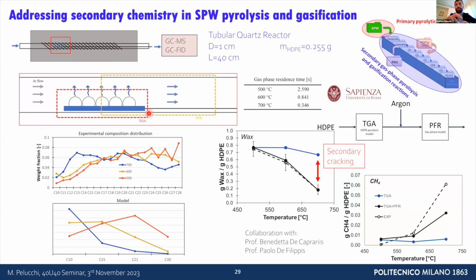So how do we model the system? Not only with a TGA, but we need to feed what comes out from a TGA to a flow reactor model, like in a simplified chemical reactor network, and couple this with the gas phase model to allow for further evolution through secondary cracking reactions.